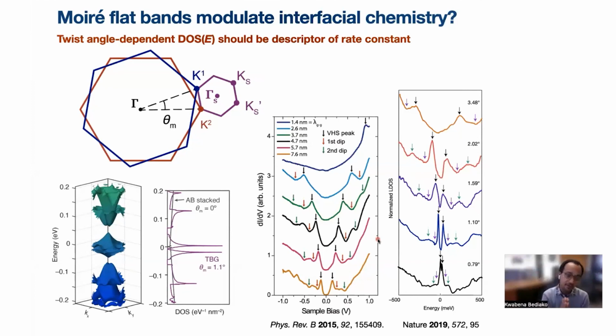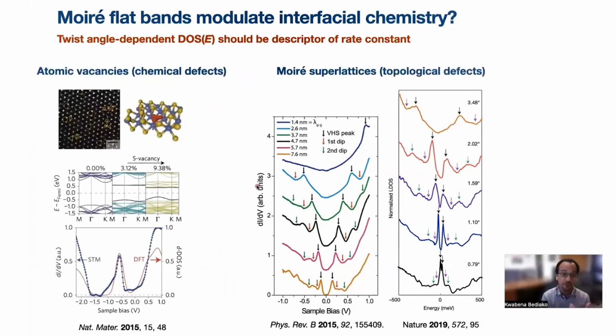And if so, then the twist angle dependent density of states should itself be a descriptor of the rate constant. And so again, looking back to this example here and thinking about how these Moiré derived flat bands might serve as reactive hotspots for chemistry, we went ahead and did this experiment.